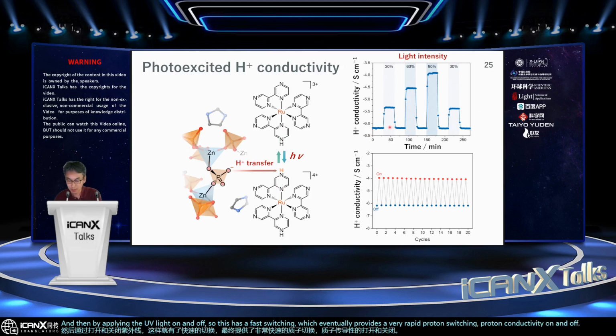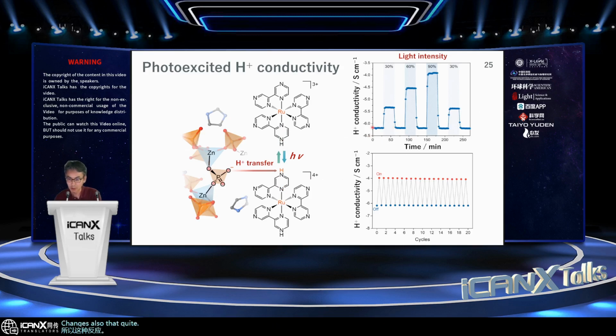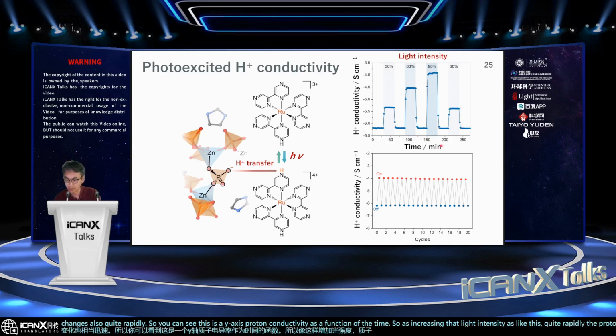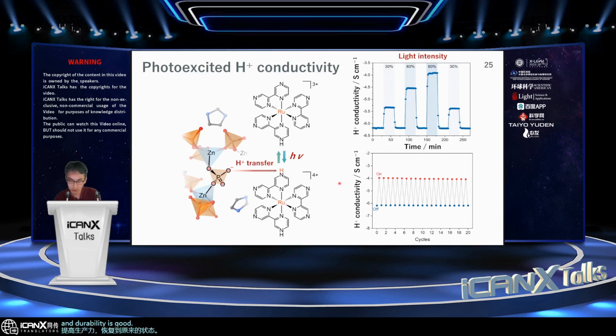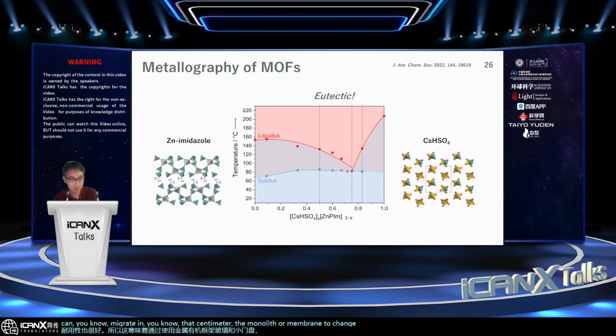The responsiveness changes also quite rapidly. So you can see this y-axis is the proton conductivity as a function of the time. As we increase that light intensity like this, quite rapidly the proton conductivity is enhanced and returns back to the original state. And durability is also quite nice. So this means that by use of that metal organic framework glass with a small dopant, we can change the ionic conductivity in a centimeter-scale monolith or membrane. So not only high proton conductivity, but this kind of switching is also possible.